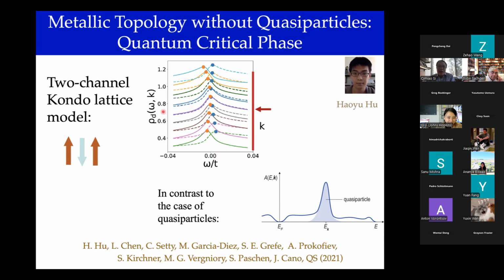And so this is captured by the spectral function, A(omega, K). It's like a theorist version of ARPES measurement: for each given K, spectral function versus omega. Instead of sharp peaks, as one would see in the quasi-particle case, these are very broad peaks. But nonetheless, one can trace out the peak locations to see that I have two branches of excitations, which are not Fermi liquid because it's not sharp, but there's a special value of wave vector K at which the two spectral functions have to be on top of each other. They have to disperse and merge at the special K for symmetry reasons, and then they disperse away from each other again. And so this is a non-Fermi liquid form of the Weyl node.